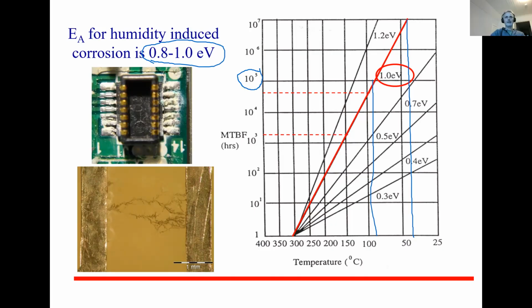If we are able to increase the testing temperature to 150 degrees, okay, this is an extreme temperature, but then the test time would be, what is that, 2,000 hours or something like that, and maybe even less than 2,000 hours. Meaning that now we are talking about testing time of 1 to 2 months. And those two would simulate a lifetime of 10 power 7 hours. So 10 million hours. So it's hundreds of years if I calculate correct. You are better in math.